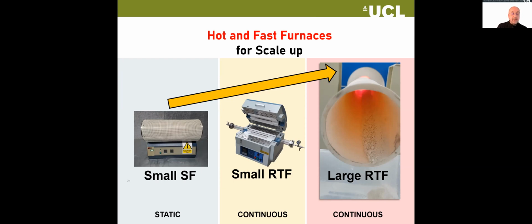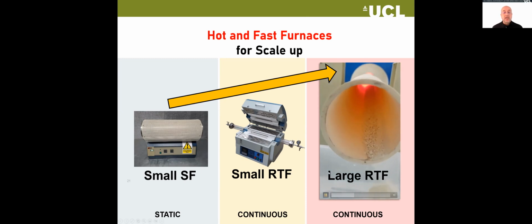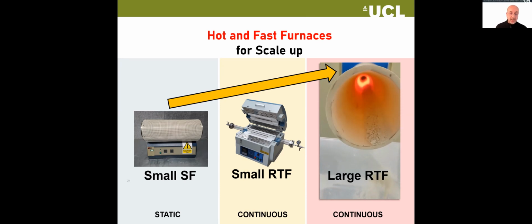After that, you've got a furnace where you introduce the powder at the top and you have an angle and it's rotating, and the material goes in at one end and comes out the other, and it might be in there for a few seconds. And you're trying to control the time and temperature based on the angle and other factors as well. It's quite complex. The third one is the large rotating tube furnace. So when we're trying to scale up, we need something that can make kilograms of heat treatment using our flash heating approach, which generally just means it's going to be for a few seconds or minutes. Anything above about 10 minutes, I don't consider flash heating.